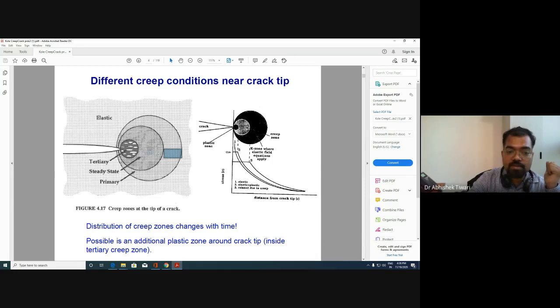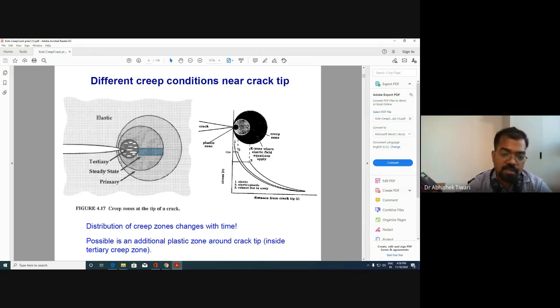Then as you come closer, in the second circle, you will have a little higher stress, and at that higher stress the primary creep will be suppressed and the material will be deforming, probably in steady state. And then very close to the crack tip, the material will be deforming in tertiary creep. So a lot of damage will be there and the material will fail there soon enough, if it crosses the material's resistance. This is similar to when you have a plastic zone at the crack tip.